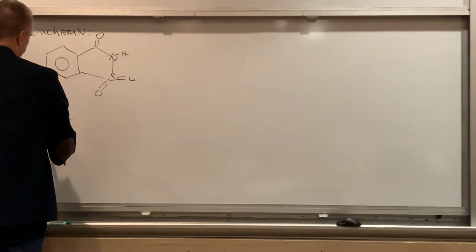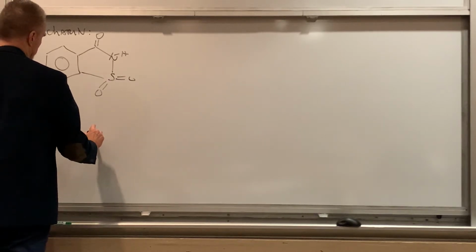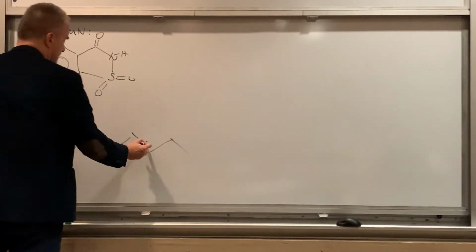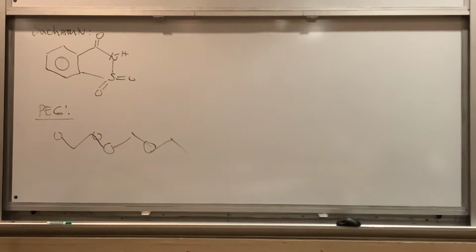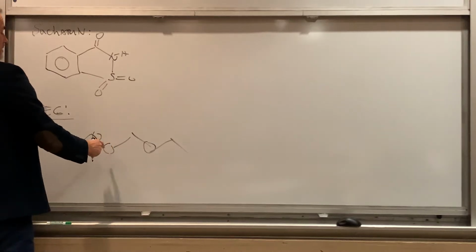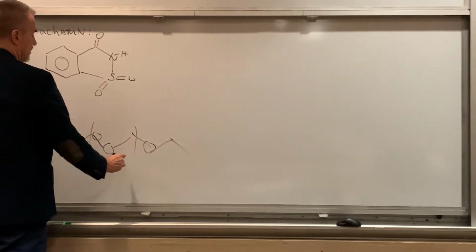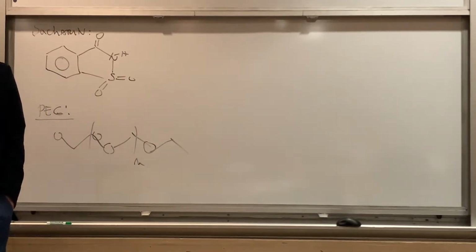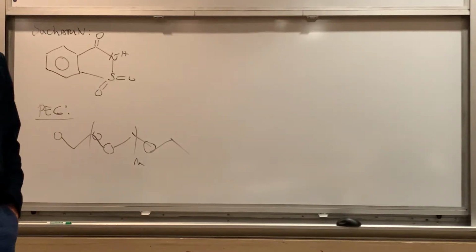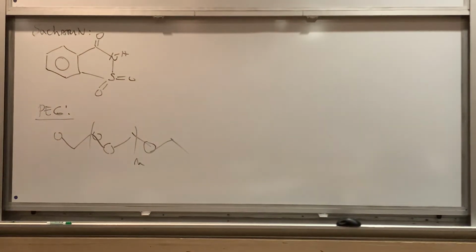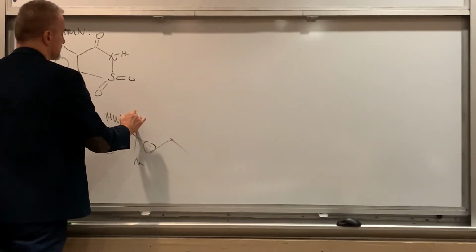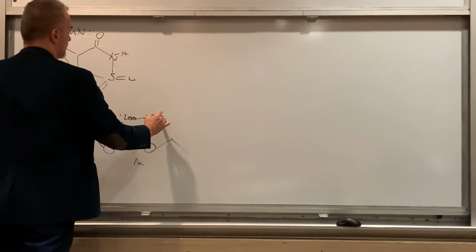And PEG is a type of polymer which has this alternating keto group or oxygen in between carbons, and depending on the length of repetition of this thing, it could have a molecular mass of 200, 400, 800, 2000. 2000 is already not soluble in water, but it can have a large molecular weight. I think what we use in electrodeposition is between 200 and 800. All right.